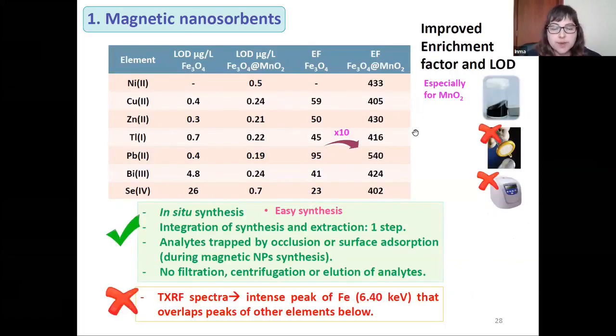In this table, we can compare the limits of detection and the enrichment factor achieved by these two types of magnetic nanoparticles, magnetite and magnetite covered with manganese dioxide. As we can see, the limits of detection are improved in all cases. For example, in the case of copper, it varies from 0.4 micrograms per liter to 0.24 micrograms per liter. Additionally, the enrichment factor can be improved in some elements by a factor of 10, for example thallium from 45 to 416. So we can see an improved enrichment factor and detection limits using manganese dioxide.